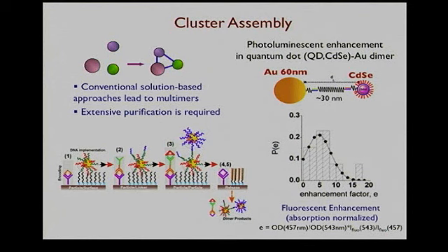And in particular conditions it has been theoretically shown that we can have significant enhancement of fluorescence properties of these quantum dots. What is shown here are measurements using single molecule techniques, which allow us basically to observe that using this type of approach and using DNA as a connector, we can establish 30 nanometer separation between surfaces, and this leads to 5-times enhancement of fluorescence properties of quantum dots.